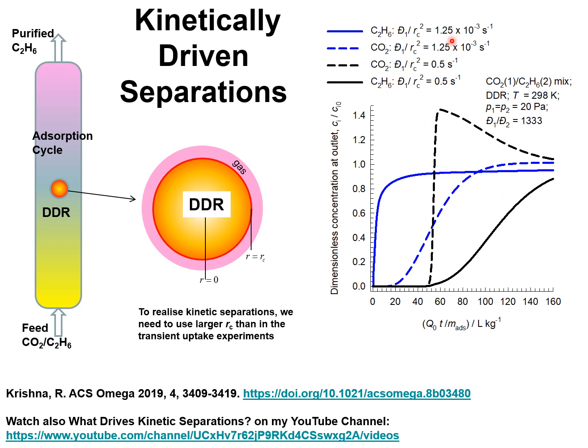So if we have strong diffusional limitation that is characterized by small values of this diffusional time constant, the component that breaks through first is C2H6. So this is the desirable scenario where we have kinetic separations dictated by diffusion that favors CO2, and CO2 is preferentially adsorbed.